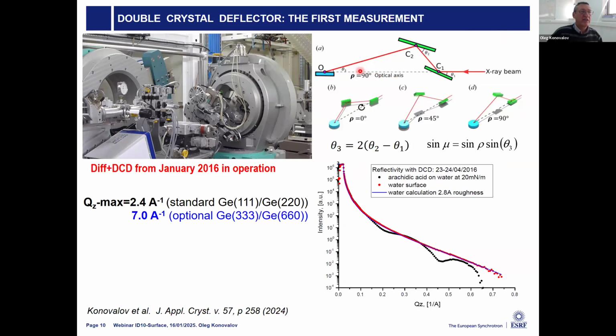And like this, we can change the scattering vector on the liquid surface, and then we can measure. Here you can see several orientations of this DCD, what we call rotation. So the 0 angle, everything, the beam, is in the horizontal plane; this is turned a bit at a certain angle, and then this is 90 degrees. This is basically this orientation. So like this, we can measure the reflectivity quite fast.